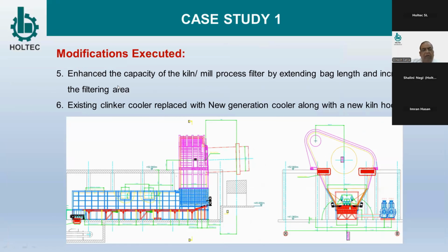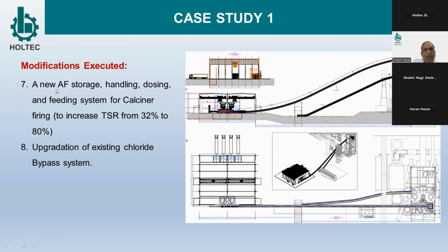Then there was a replacement of the cooler. A new generation cooler was installed, and the process filter was also extended for the kiln, and the main bag filter was also extended. The capacity was increased, and with the cooler, the hot hood was also modified accordingly. The original hood was very small. And then, of course, a new AF storage, handling, dosing and feeding system for the calciner was put up for increasing from 32 to 80%.